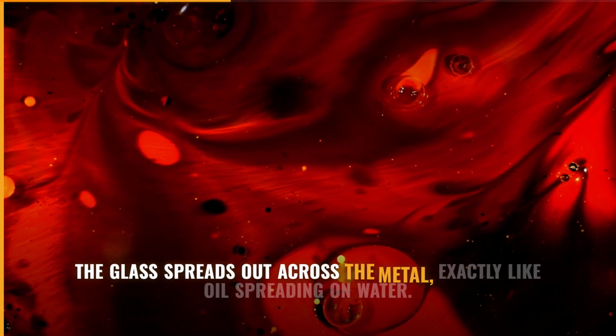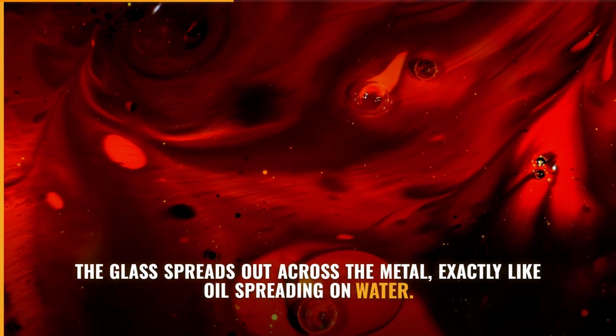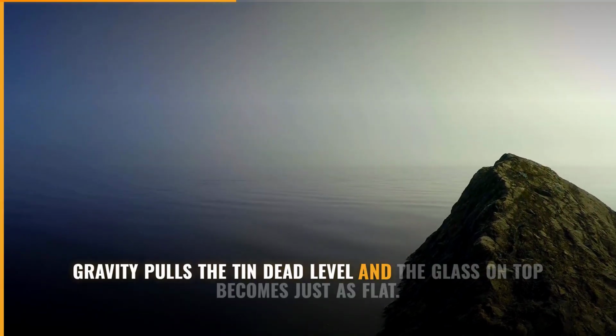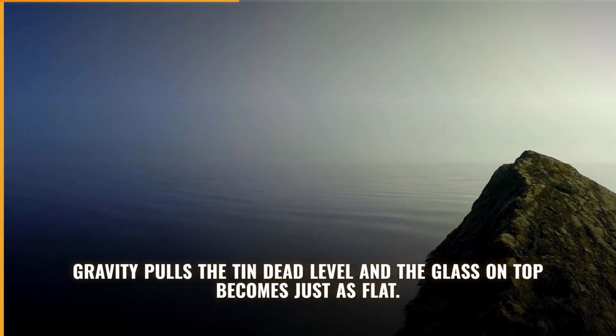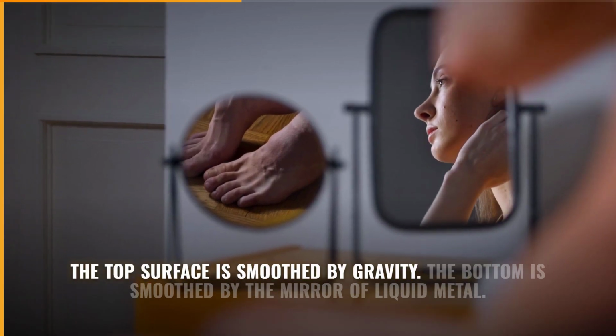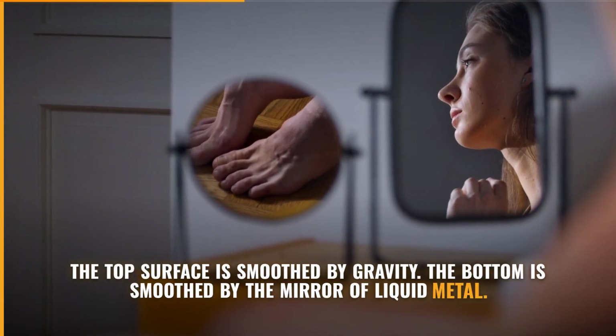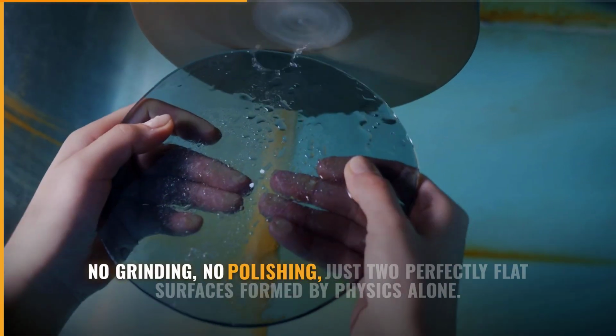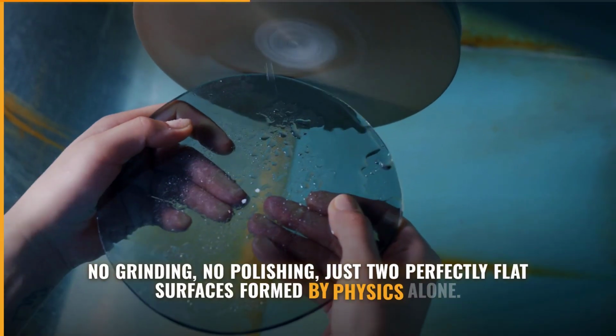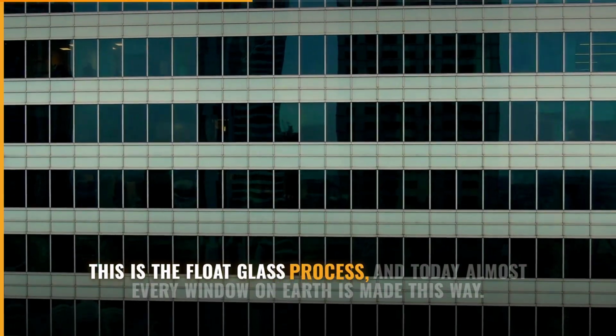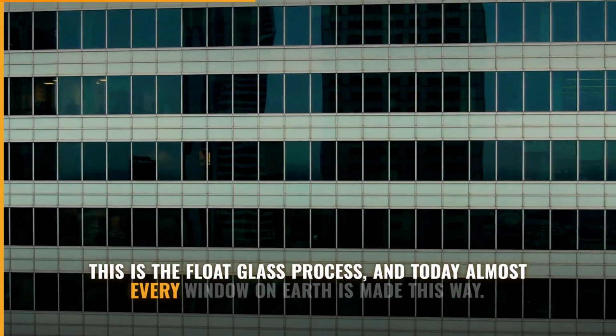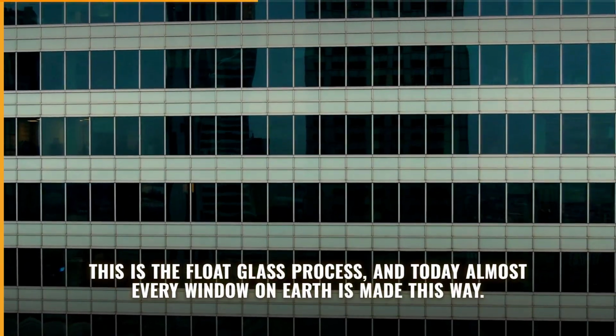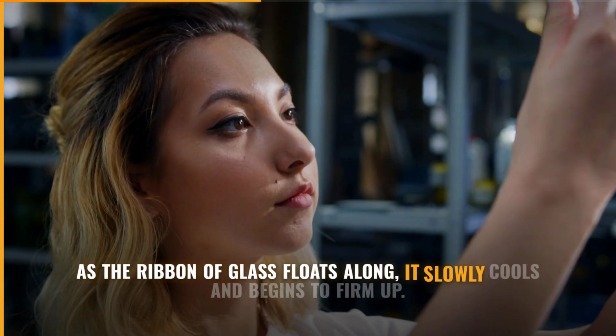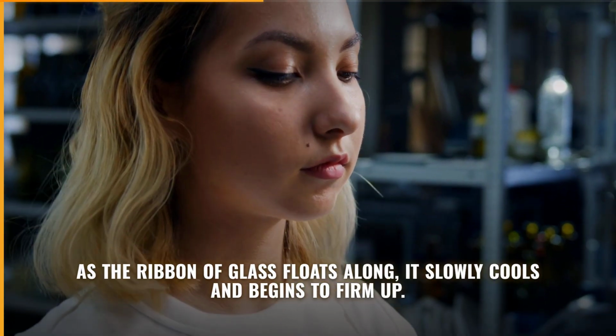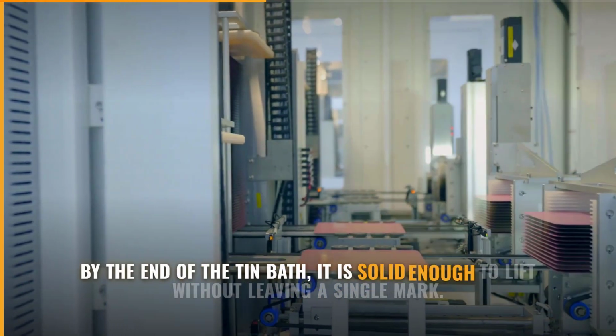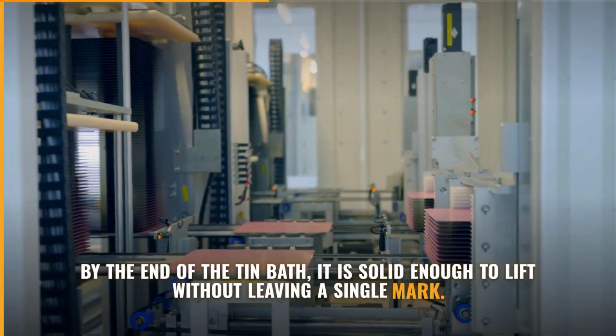The glass spreads out across the metal, exactly like oil spreading on water. Gravity pulls the tin dead level, and the glass on top becomes just as flat. The top surface is smoothed by gravity. The bottom is smoothed by the mirror of liquid metal. No grinding, no polishing, just 2 perfectly flat surfaces formed by physics alone. This is the float glass process, and today, almost every window on Earth is made this way. As the ribbon of glass floats along, it slowly cools and begins to firm up. By the end of the tin bath, it is solid enough to lift without leaving a single mark.